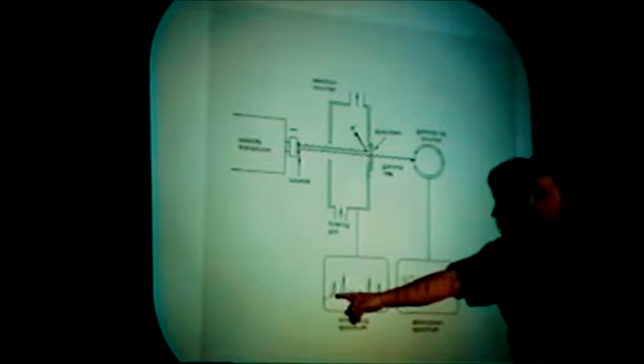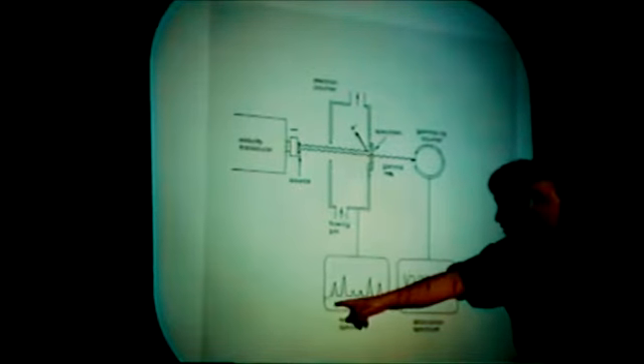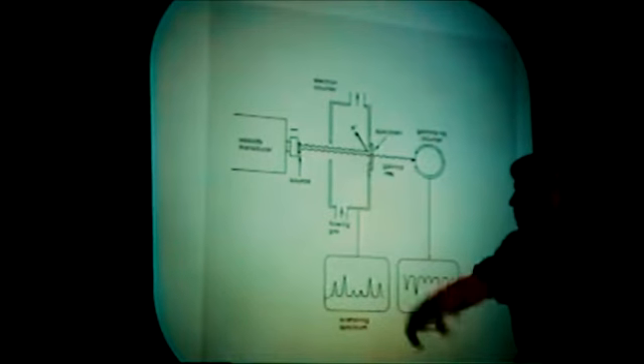It will not escape as gamma rays, but it goes and knocks off electrons. Okay, and then on top of the non-resonant electrons coming out of the material, you have the electrons knocked out by resonance. So you have a large number of electrons coming out when you have resonant absorption. If you count the electrons, you see the number of counts at resonance goes up, and you will collect a spectrum where the peaks are pointing upward. This mode is good if you're studying thin films or very thick films, for example, where the gamma rays cannot escape, like to study corrosion on a bridge. You build a detector around the piece you'd like to see, and you start to see iron oxides there.